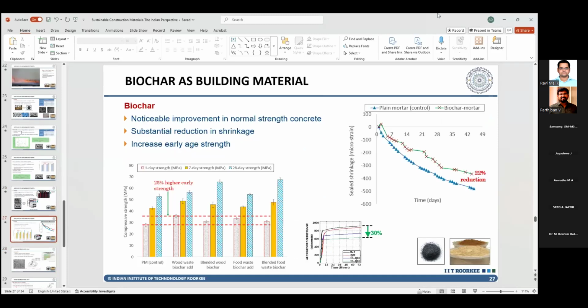The same is the case with normal concrete. You can see a large reduction in shrinkage if you're using biochar. And as I've said, you can also see high early strength if you're using biochar, provided you have prepared it correctly from a correct feedstock.